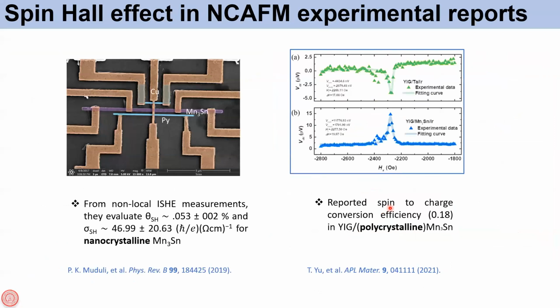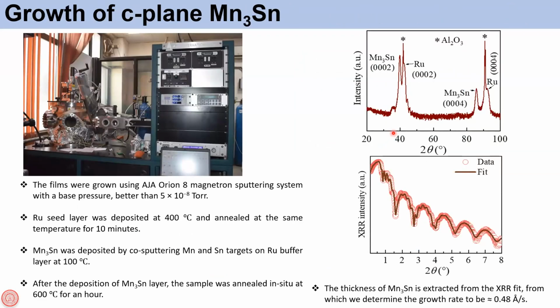There were also previous experimental works which showed evidence of the spin Hall effect. In this one, for nanocrystalline Mn3Sn, they found some spin Hall conductivity. And here is another work on polycrystalline Mn3Sn, where they also observed a spin Hall effect. But there was no work on C-plane Mn3Sn. So we tried to grow epitaxial C-plane Mn3Sn.